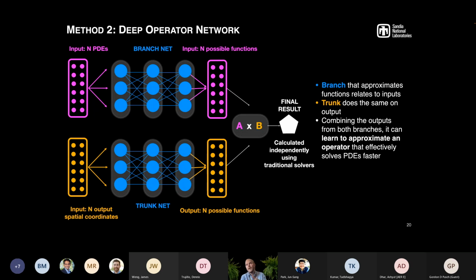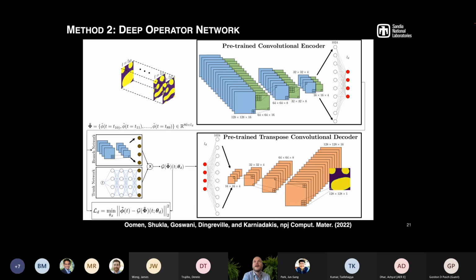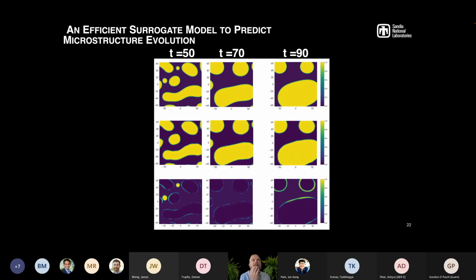And then you basically do a combination or a product of these two networks to approximate your operator. In this case, we used our autoencoder architecture to describe the microstructure. Then that latent representation was fed into our DeepONet architecture. The DeepONet was predicting the evolution of the microstructure, learning that mapping in the low dimensional space. Once you have the evolution of your low dimensional space, you can use your decoder to retrieve your microstructure at some point. And so what you get from this is an efficient surrogate model that also predicts the microstructure.